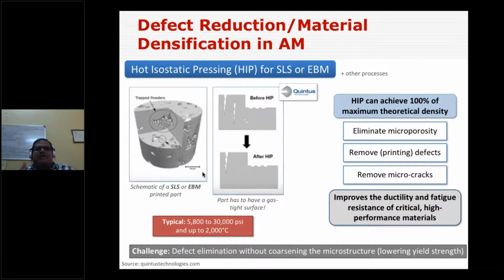So in a similar way, you have the hipping process here, and the pressure may go up to 5800 or 30,000 psi, and the temperature may go up to 2000 degrees C. That is the typical hipping process which you may use, and this hipping process will achieve 100% of the theoretical maximum density, which eliminates microstructural porosity and removes the printing defects.